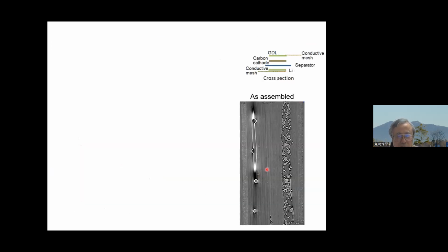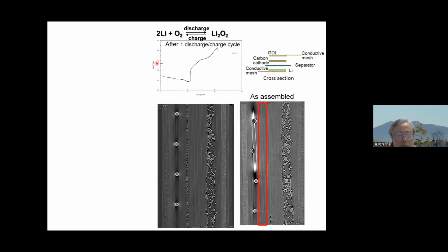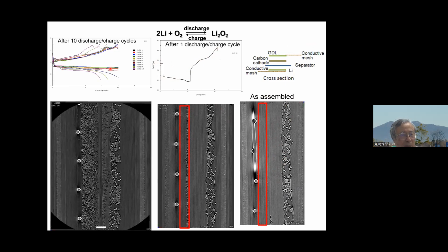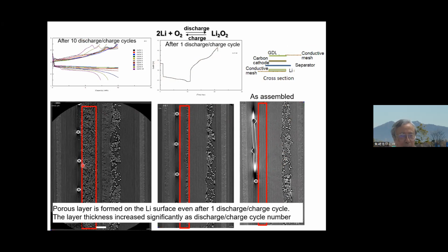So this is the X-ray CT image before the discharge. We cannot distinguish lithium metal and the separator, but once we do even just one discharge charge cycle, you can see there's a porous layer on top of the lithium metal. And then after 10 cycles, the lithium became very porous and very bad. So this is another cause of the degradation.